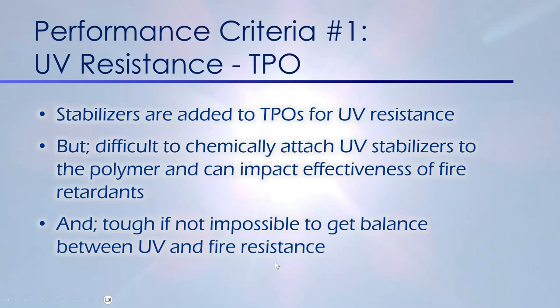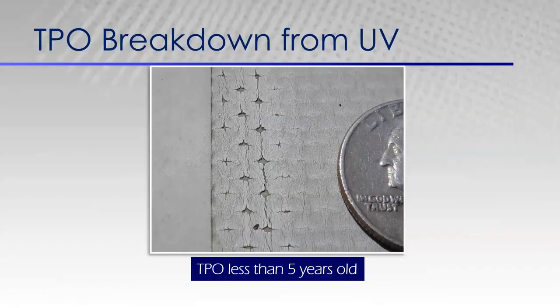So let's take a look at our next slide. Here is an example of a TPO roof that is less than 5 years old. Most of your failures on the roof are going to happen at the seam first. So this is a seam, and you can actually see the seam there where it is starting to break down due to the UV exposure and dry out. So again, this is a TPO that is less than 5 years old. And again, finding that sweet spot between fire resistance and UV resistance has been very difficult for the TPO manufacturers to achieve.